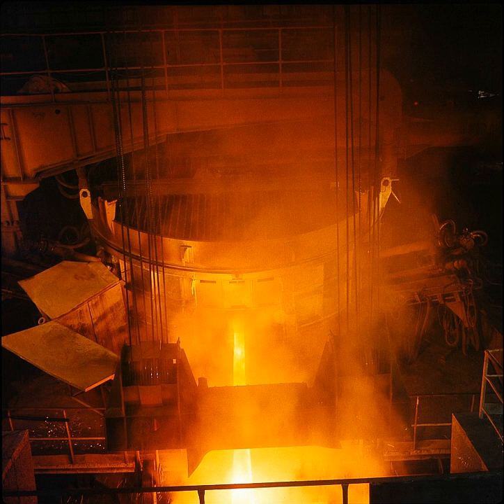However, while a tubular leak is immediately noticed in an operating furnace due to the pressure loss alarms on the panels, at this time there exists no immediate way of detecting a very small volume spray cooling leak. These typically hide behind slag coverage and can hydrate the refractory in the hearth, leading to a breakout of molten metal or, in the worst case, a steam explosion.